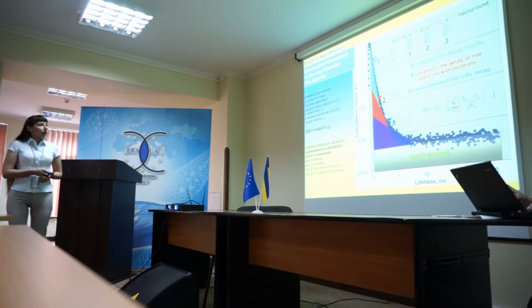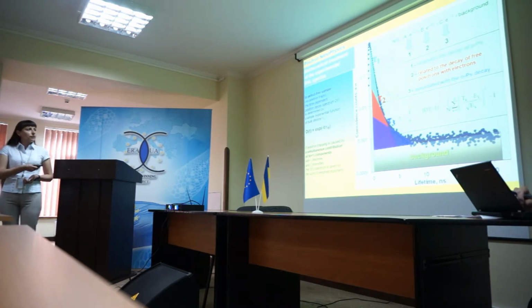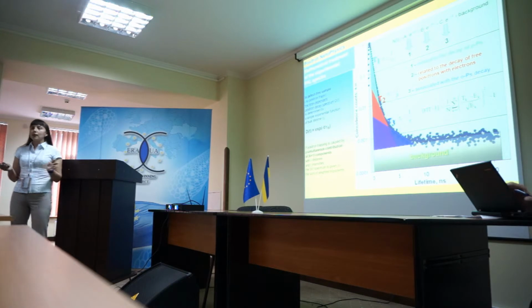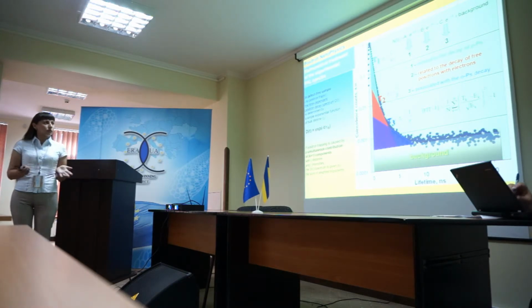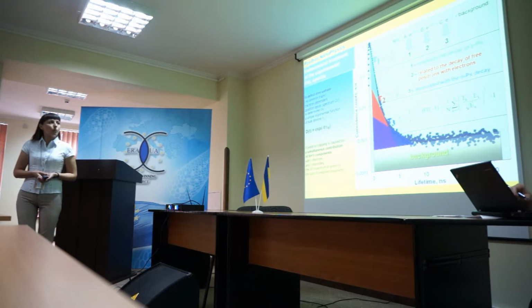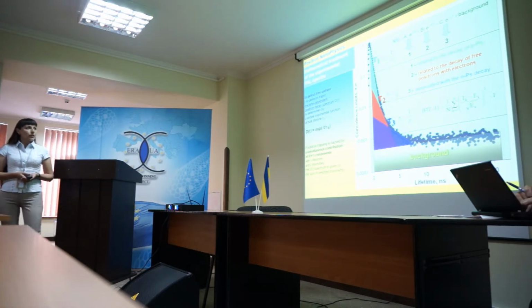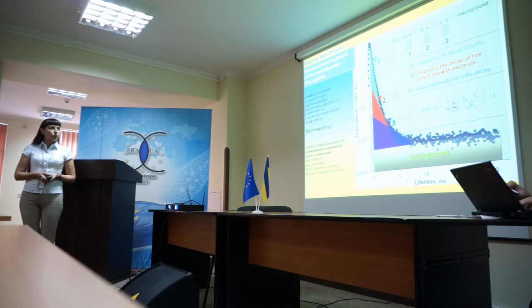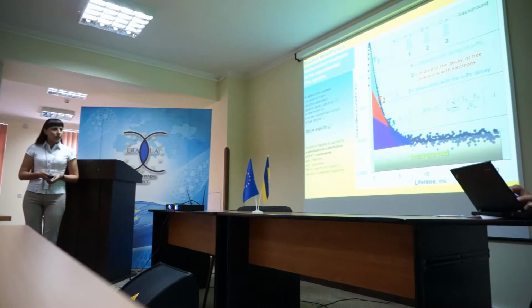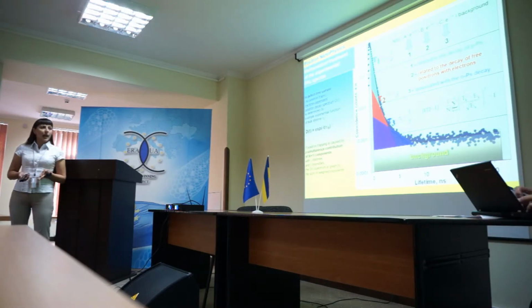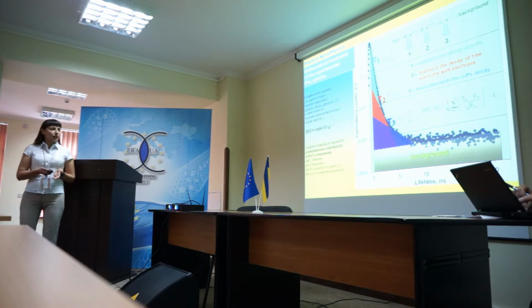In the results we obtain spectra with mathematical treatment into three components. The first one is related to the decay of parapositronium, the second one related to the decay of free positrons with electrons, and the third associated with orthopositronium decay. In our materials, in some parts, we have only two components, first and second. It depends on the specifics of the materials and the size of voids in these materials.